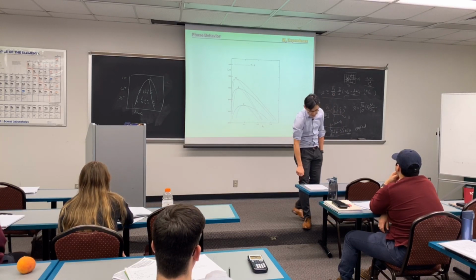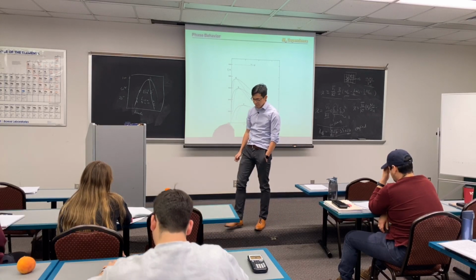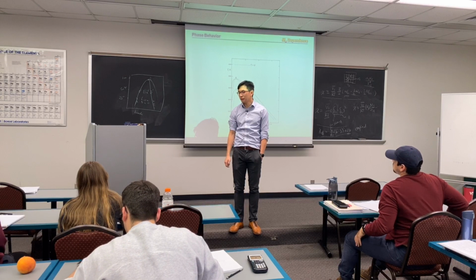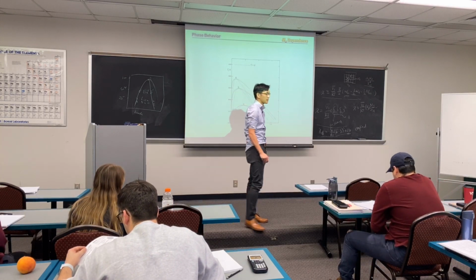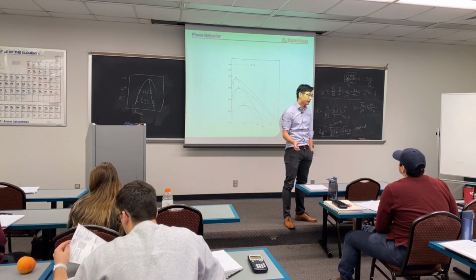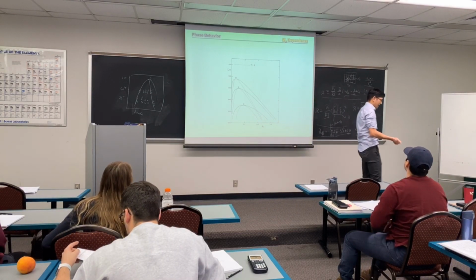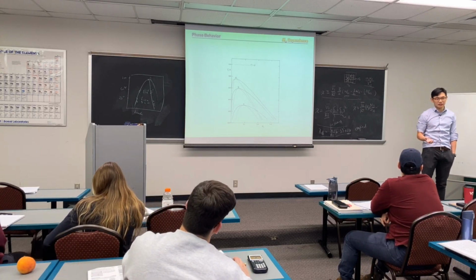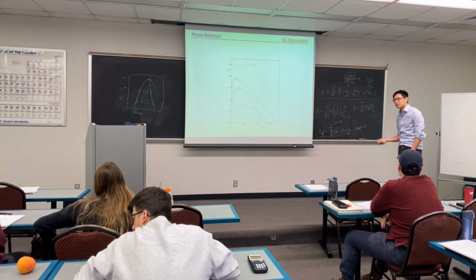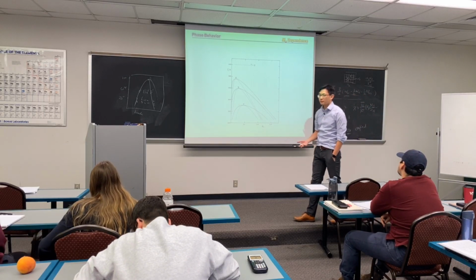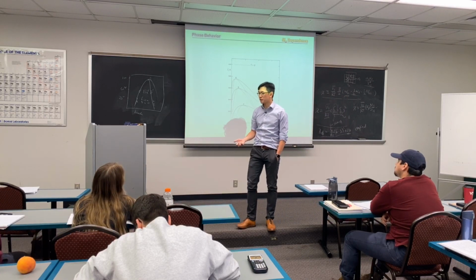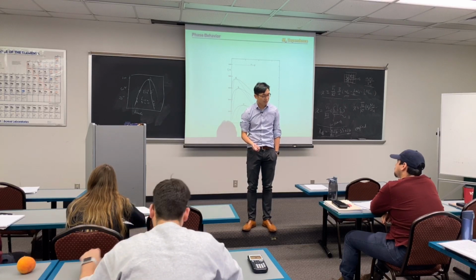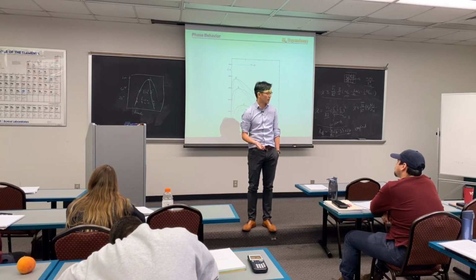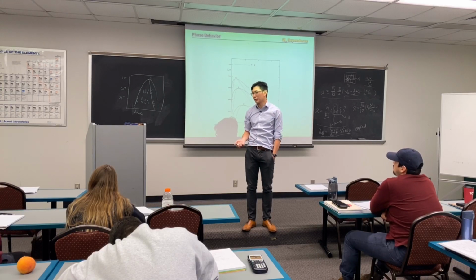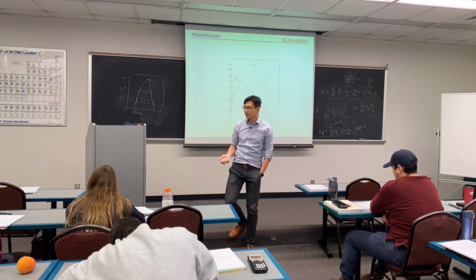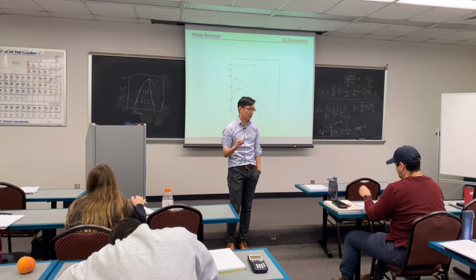Okay, so for the last part we can just chat a little bit about what solvent quality is. We already talked about it in the first lecture in terms of chain conformation, so we're just going to briefly recap. Remember the scaling law, how Rg depends on the molecular weight. In good solvents, Rg depends on molecular weight to the power of 0.6. That comes from the excluded volume effect. And in the theta solvent, Rg depends on molecular weight to the power of 0.5. That's the ideal chain. And we also know for the collapsed globule, you would have Rg depends on N to the 1/3. That's related to the diameter of your sample.